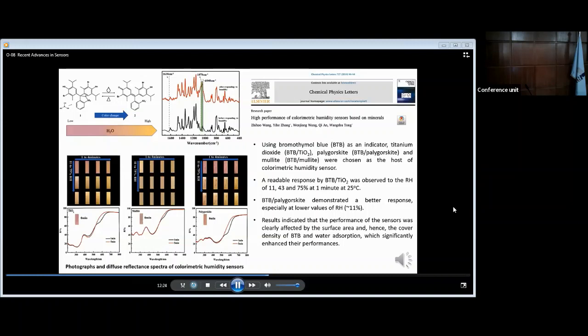The BTB/palygorskite demonstrated a better response, especially at lower values of relative humidity around 11%. Results indicated that the performance of the sensor was clearly affected by the surface area, and so the capability of BTB and water absorption would significantly enhance their performance. And you can see here the change in color, the color of bromothymol blue in response to change in the value of relative humidity.